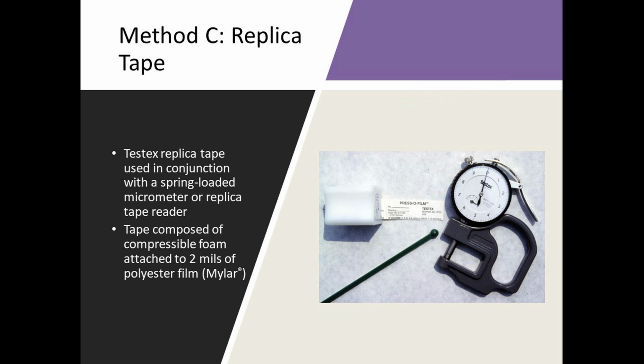Side. So basically, after removing the paper backing, we attach the tape to the surface and literally burnish the tape with the burnishing tool. And what that does essentially is it creates a mirror image of the surface profile in the foam that's on the back side of the tape. So you're creating an impression of the surface profile.